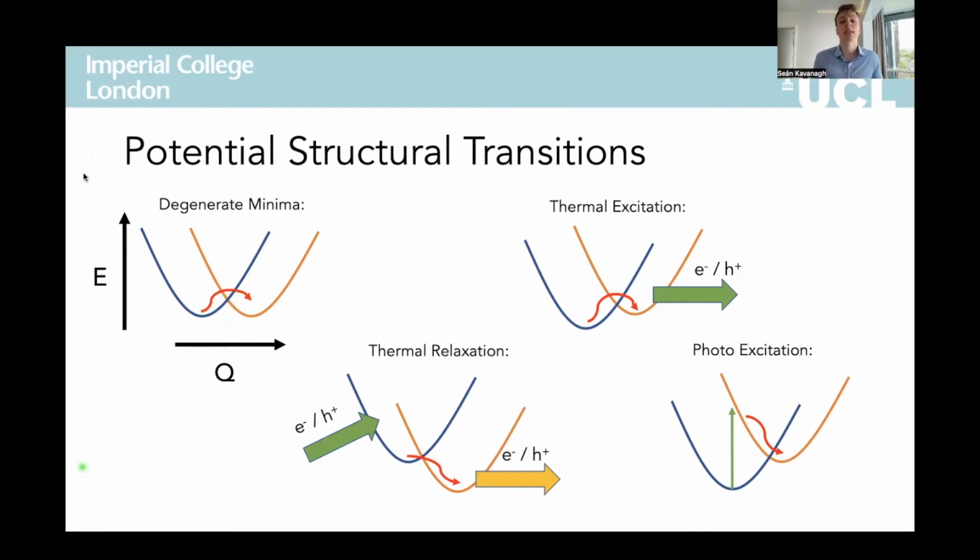While this is unlikely to significantly affect the recombination behavior, it is important in the context of comparisons between theoretical and experimental measurements of defect structures, as depending on the experiment temperature and timescale, the defect may appear more localized and anisotropic than is truly the case under operating conditions.